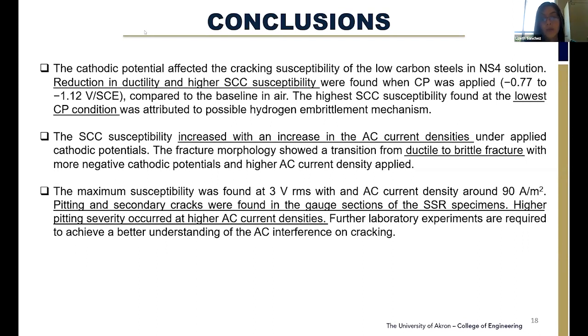For example, for the -0.77, the result is that there is a transition from ductile to brittle when the AC is applied. For the lowest cathodic potential, we found pitting, the pitting was severe in these conditions, and the fracture morphology was pretty similar with and without AC voltage.